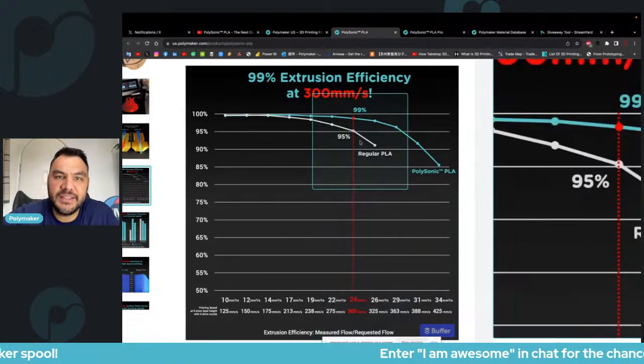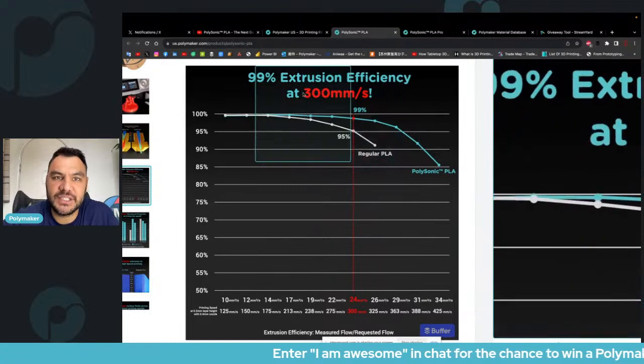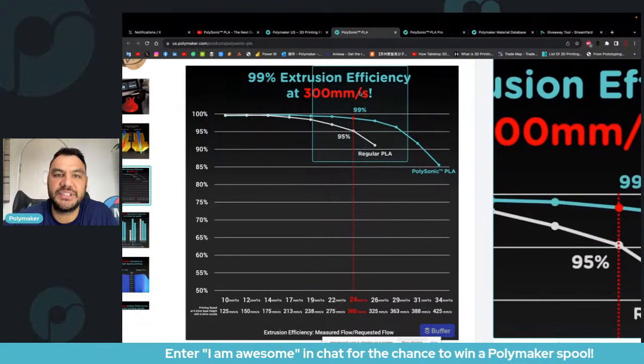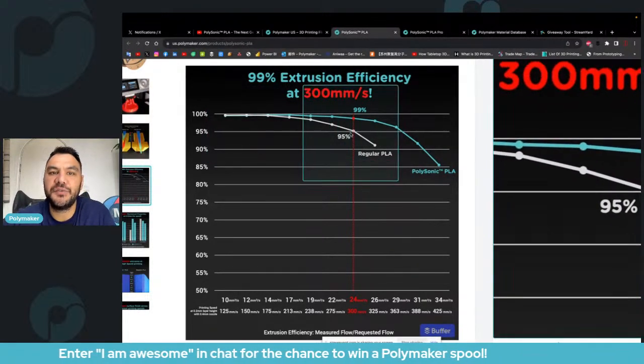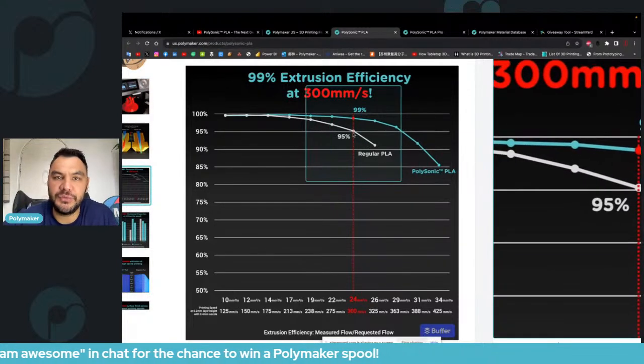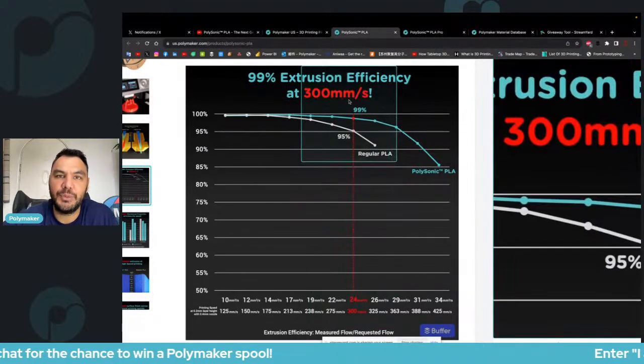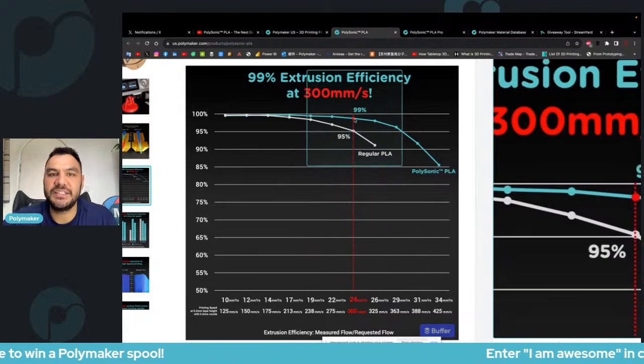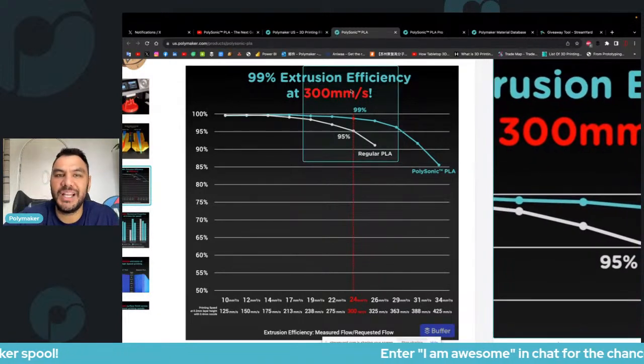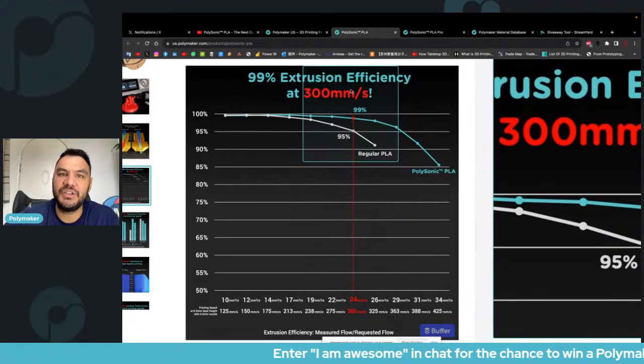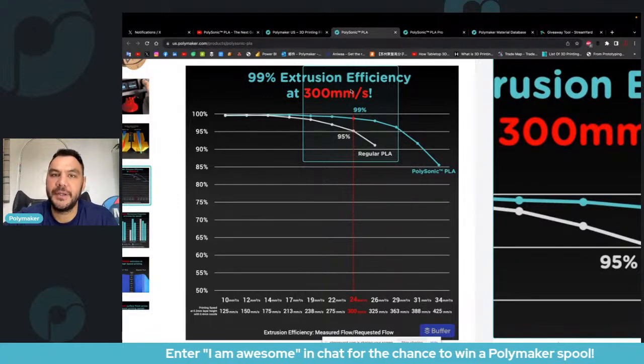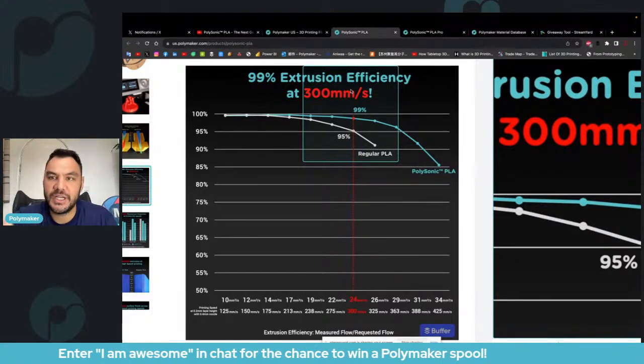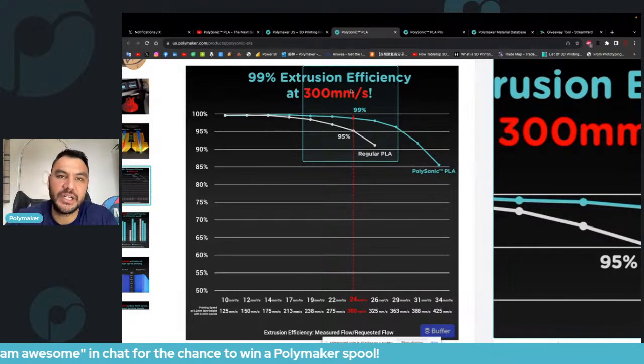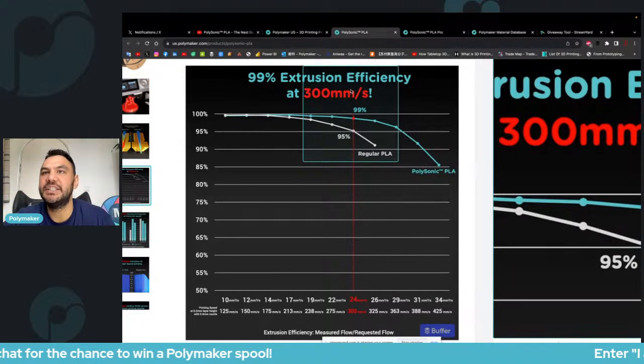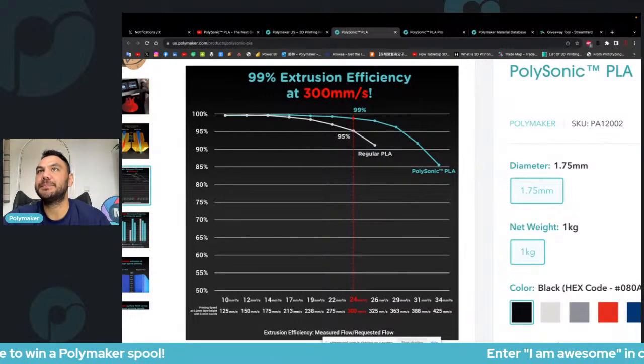So in that case, our Polysonic PLA has an extrusion efficiency of 99% compared to 95% for regular PLA. So if you print with regular PLA at that speed, you will have much more issues than this. But one issue you will have is 5% less material than you're supposed to have. And that affects a lot of things, right? Mechanical properties, dimensional accuracy, surface quality.